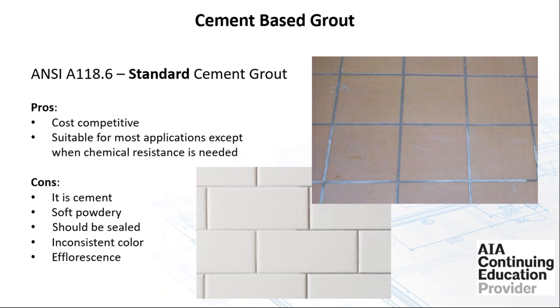So I'm sure we've all seen these pictures, specifically that top one, where you've used ANSI A118.6 cement grout. The installer comes back at the end of the day, does that one or two extra passes with a wet sponge. That charcoal grout looks beautiful at the end of the day. Come back the next morning and it's inconsistent. Charcoal is either silver or, like we see here, kind of blotchy. What's happening there is the water is pulling the pigment out of the grout and it's basically drowning it out. It's becoming inconsistent because we do have pigments within the makeup of the product.